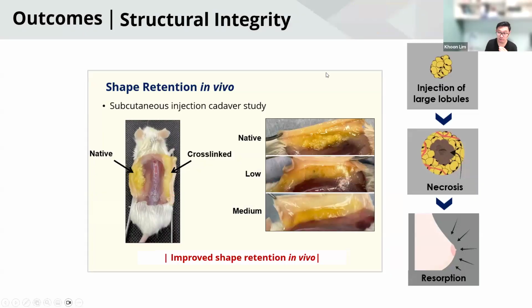What we thought is most encouraging is this, where native fat that is not crosslinked, as I mentioned earlier, you can see that they start forming globular structures. So now they're starting to agglomerate under the skin. But if you slightly crosslink it with our visible light photoinitiator, you can see better integration with the underlying skin. What we believe is because the photoinitiators can introduce these dityrosine crosslinks, on the skin you should also have some inherent extracellular matrix molecules that have tyrosine. So you potentially are stitching the fat to the skin, so you get much better integration and better shape retention.